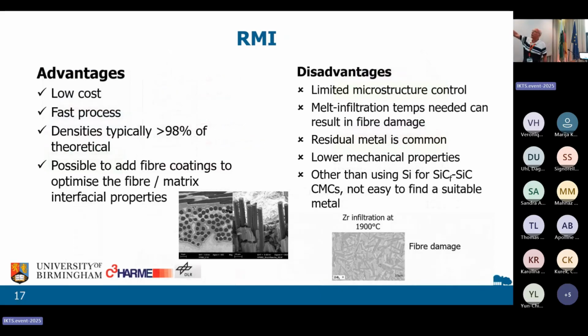So the advantages: low cost. It's a fast process. It really is very fast. It's a matter of just a few minutes. Greater than 98% density. That is fantastic. And it's possible to add fiber coatings. Limited microstructural control. You do get fiber damage unless you can protect your fibers appropriately. Residual metal is common. Now, that's the problem.